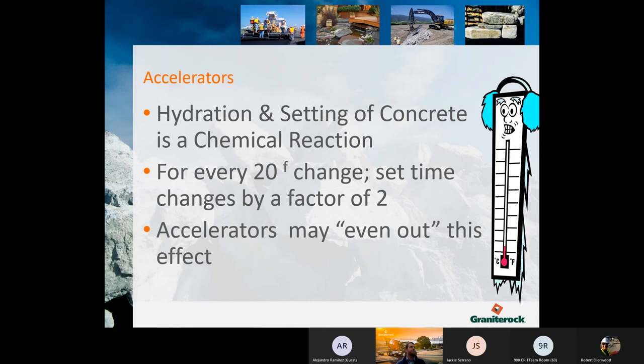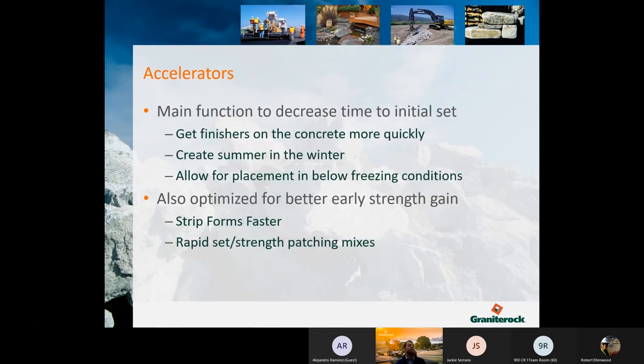On the flip side of that, we have set accelerators. It affects the hydration and setting of concrete, which is a chemical reaction. The accelerator basically expedites that. Rule of thumb is for every 20 degrees Fahrenheit change, the set time changes by a factor of 2. And accelerators can help even out. So if it's 40, 50 degrees, the concrete would be acting and setting very slow compared to, say, 70 degrees. And this can help speed up the concrete to a more normal time.